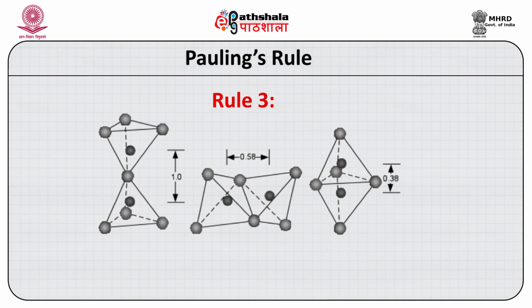The farthest distance between same charge particles leads to a more stable structure. Reduction of this distance, say in case of sharing of edges to 0.58, leads to less stable structures, and further when the faces are shared it becomes 0.38 and the structure is less stable.